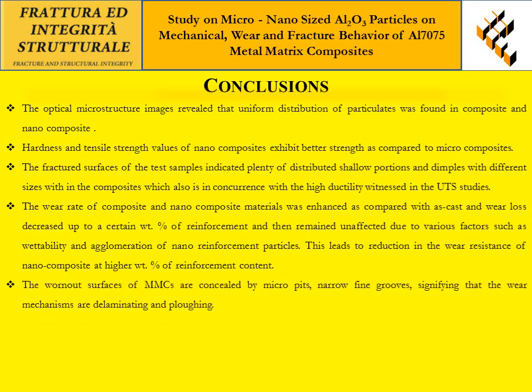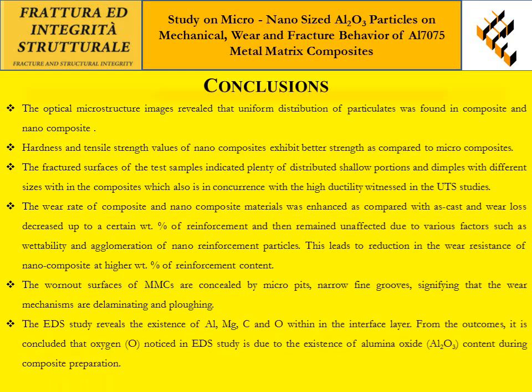The worn out surface of the MMC signifies that the wear mechanisms are delaminating and ploughing. EDS study reveals the presence of Al2O3 content within the composites.